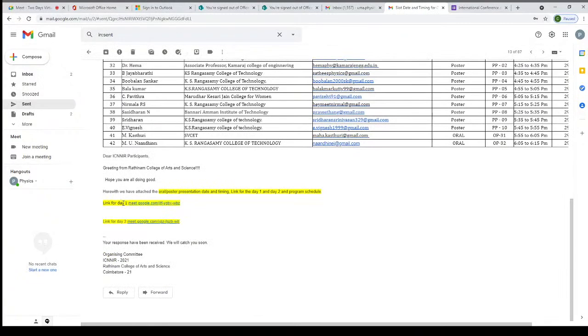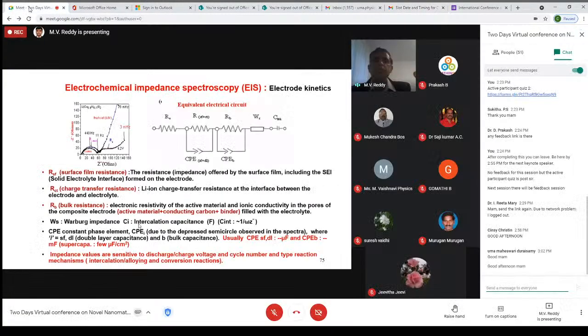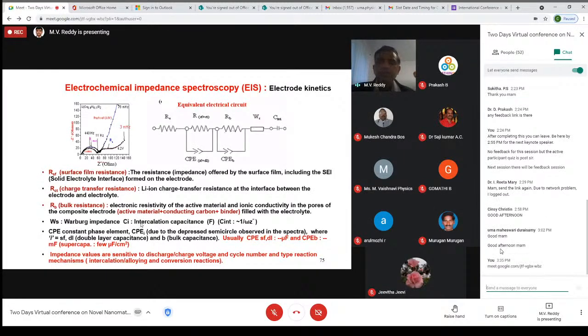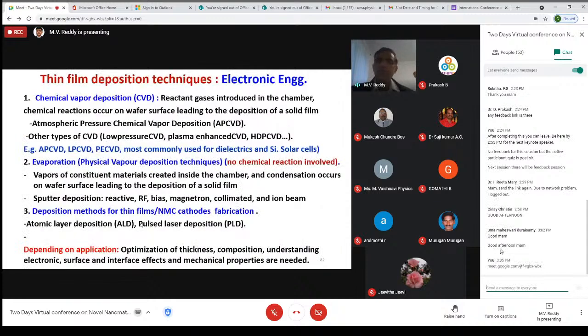Typically we may get, depending on the cell, a single semicircle, in the sense that without charging a battery, and after charging we can get one to two semicircles. For example, charge transfer will come from here, and bulk resistance. So it is very important, depending on which type of materials, for example, which type of solar cells, that we use proper explanations. Again, we need knowledge of materials, and an understanding of both chemistry and physics, etc.